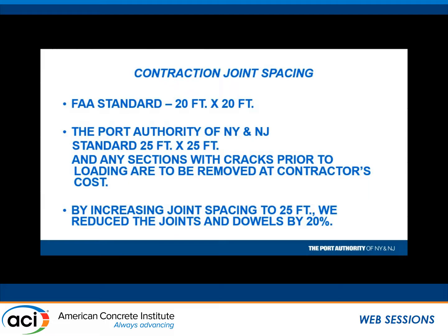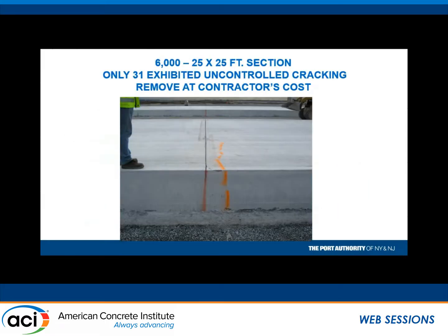Well, just watch. Here's the way you put the words in the spec. And we did that. And you know what? It turned out very good. There was roughly 6,000 slabs for that runway, 25 by 25. Only 31 were removed because of cracking prior to opening.